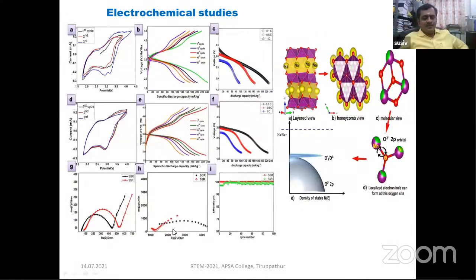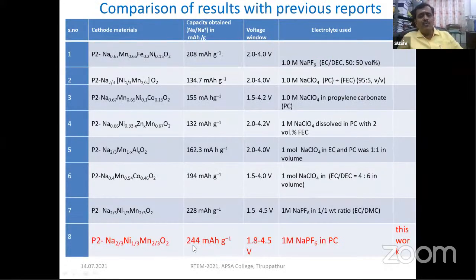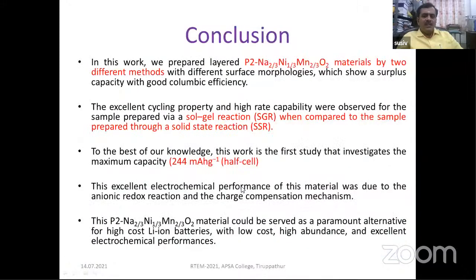It gives the hexagonal P2 type structure, and it exhibits greater than the original theoretical capacity. The original theoretical capacity of such material, sodium nickel manganese oxide, is 173 milliampere hour per gram, whereas we got more than that, around 244. It is due to the voltage range 1.8 to 4.5, while we are using NaPF6 in propylene carbonate. This is because of the anionic redox reaction of the P2 type